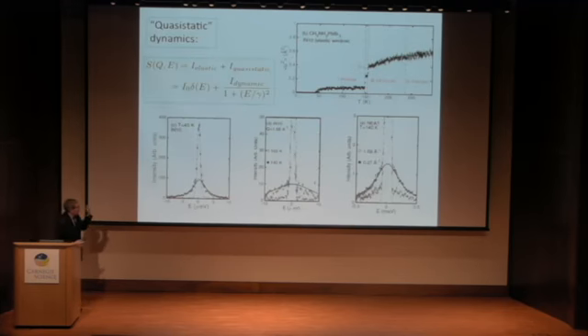One of the nice things with neutrons is we can scan perpendicular to this axis and investigate what happens as a function of energy transfer. That's what I'm trying to show down here in these three graphs. First of all, if you look at the lower left-hand corner, I've plotted the intensity, but now as a function of energy transfer, right at around 50 Kelvin, where we start seeing dynamics enter into the spectrometer window.